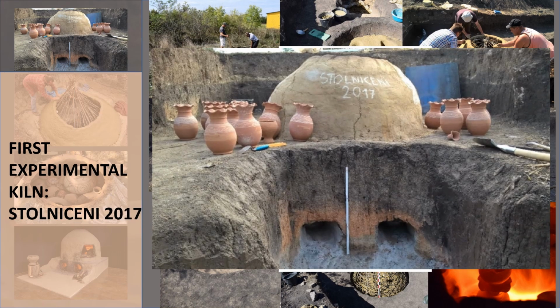One key issue identified was the excessive width of the top opening, which allowed heat to escape instead of being retained. Additionally, the kiln's underloading may have prevented heat from building efficiently. Despite these setbacks, the experiment successfully demonstrated the general viability of the Cucuteni kiln design, while highlighting areas for refinement.